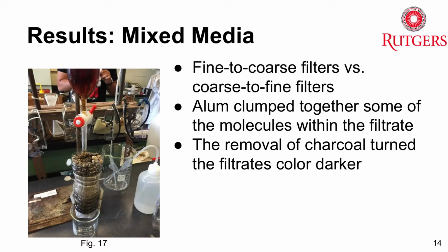Regarding our mixed media filters, we found different pros and cons to both fine to coarse and coarse to fine filters. Fine to coarse filters work better than coarse to fine filters in that they are able to get out more contaminants. However, the fine to coarse filters also take a lot more time to filter out materials than the coarse to fine filters. In addition, when we ran water with food dye through both of those filters, we noticed that the coarse to fine filters were able to take out most of the food dye, while the fine to coarse filters didn't work really at all.